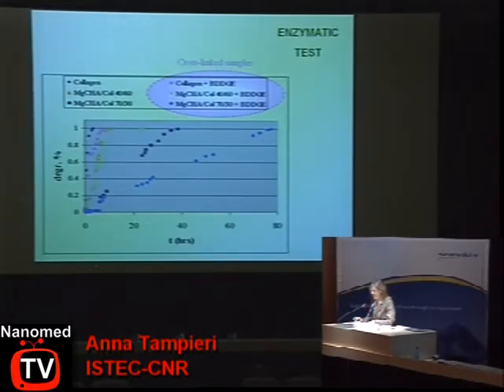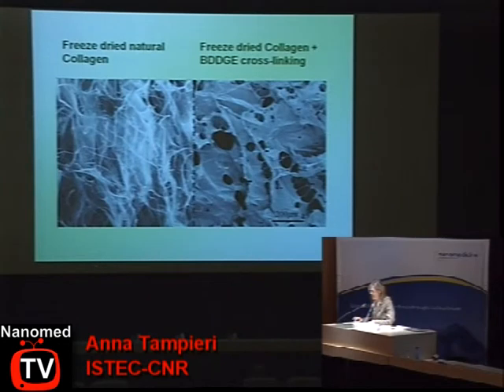This is an enzymatic test showing that mineralized collagen is protected, is stabilized, but we also need a cross-linking agent, like, for example, BDDGE or genipin. There are a lot of well-tolerated cross-linking agents, and we can stabilize the composite. This is the morphological effect of a cross-linking agent.